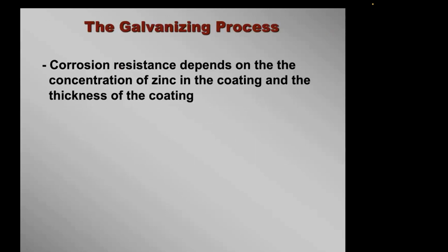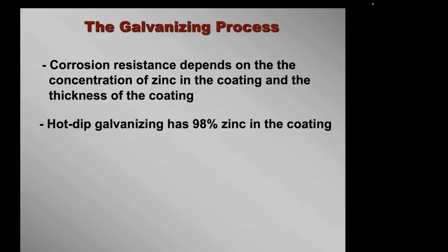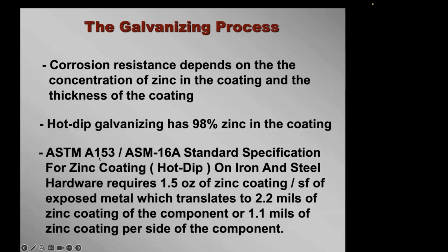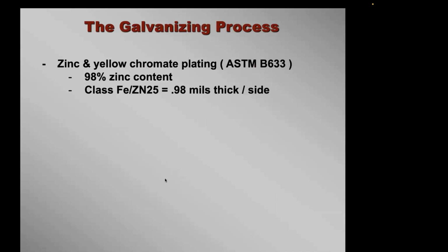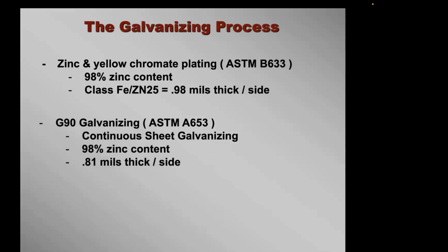And in talking to the American Galvanizing Association, they were telling me the corrosion resistance depends on the concentration of zinc in the coating and the thickness of the coating. So the hot dip galvanizing has 98% zinc in the coating. This ASTM A153 that's been around longer than I have states this, and it requires 1.5 ounces of zinc coating per square foot of exposed metal, which translates to 2.2 mils of zinc coating or 1.1 mils of coating per side of the component. So zinc and yellow chromate under ASTM B633 is 98% zinc, but the highest class that they have, the Fe/Zn 25, is only 0.98 mils thick per side versus the 1.1, but it's pretty darn close to hot dip galvanizing. Your G90 galvanizing is 98% zinc, but it's only 0.81 mils thick per side.